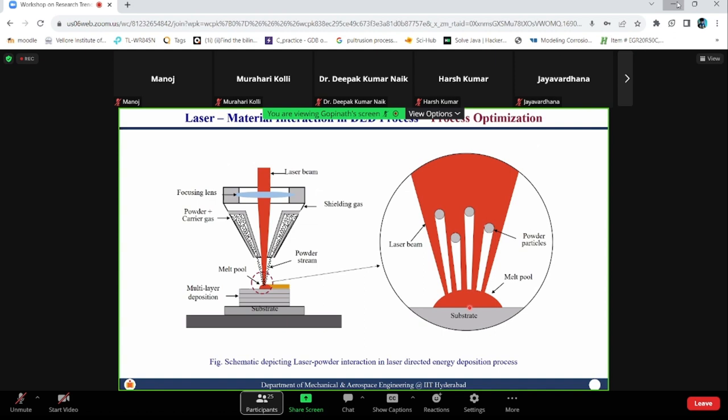Am I correct? Because the 20 mm SOD is with respect to the valley, whereas these points are above the 20 mm level, meaning the standoff distance is 17, 16, 15 or 14 and so on. Now what will happen? There will be a higher amount of deposition in the valley and a higher amount of melting at the peak. So if you choose this very judiciously, then your peaks will get melted and valleys will get filled. Are you getting this point?